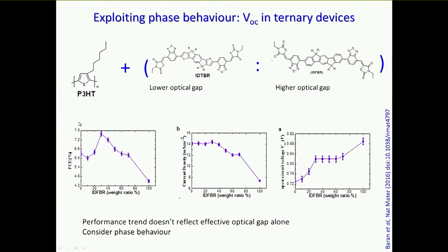The thing I would then want to finish on is a very final example, touching on the same concept, where we have the same polymer as in the previous study, but instead of a fullerene we used alternative acceptors, and not one but a combination of two of them in different ratios. We call these non-fullerene acceptors. Typically, if you have a ternary system, a polymer and something else, and you change its properties linearly from one regime, in this case higher band gap to lower band gap, you might expect a monotonic change in the resulting properties.